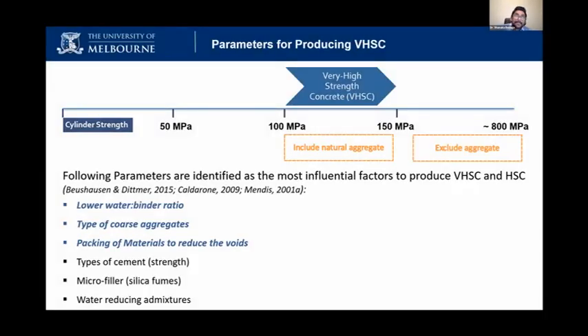So as I mentioned, 100 to 150 megapascal we can produce using natural aggregate, but we usually can't produce more than that using natural aggregate. If you produce something more than 150 megapascal, we have to exclude the aggregate. But if you're going to develop something more than 100 megapascal, the critical factor is the aggregate, because the quality of aggregate is so important. If there's a defect or the aggregate consistency is not similar, that really affects the strength.